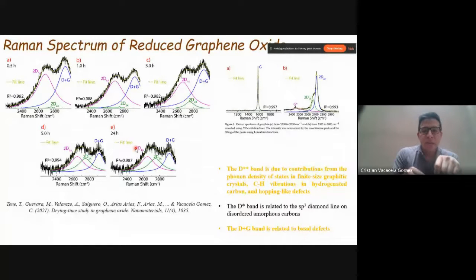That's very good because we have a corrugated structure. And after the reduction time, we are removing the oxygen functional groups, which means that we are trying to recover the intrinsic properties of pristine graphene. But of course, it's not possible to get a single layer graphene by using the chemical reduction process. If you remember from the previous slide, the 2D band gives information about the stacking and the number of layers. Here we can see that we are recovering the graphitic-like structure, or in other words, we are trying to recover a layered structure after the reduction process.